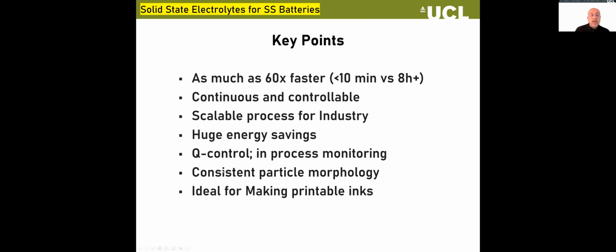And obviously, what you can do here is you can keep taking samples and monitor the quality of the material that's coming out through XRD, and that's what we were doing. And it's perfect for making printable inks because you're controlling the particle size to a degree, whereas when you use solid state chemistry, you're basically heating and grinding it, and it's very hard to control the morphology of the crystals. And in fact, what you're getting out is a very sort of jaggedy, broken up powder often, so it's not easy to disperse.